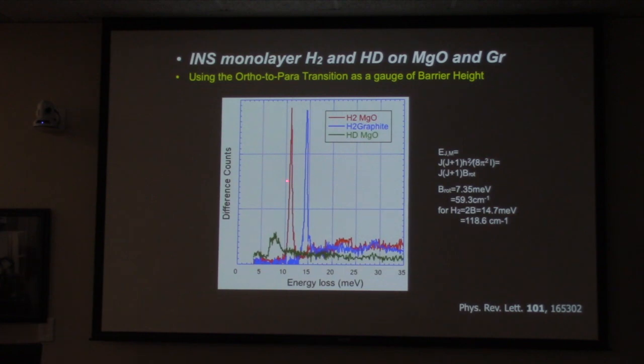We know that this is a rotation because if we substitute H for D, and there's where you pay a big price in the scattering cross-section, it moves down by the ratio of what's called the reduced mass, right? It gets a little bit heavier, so the moment of inertia is a little larger, and so it slows down. And you see that. Keep that in mind. So this experiment right here at the ISIS spallation source took 2 days to measure.